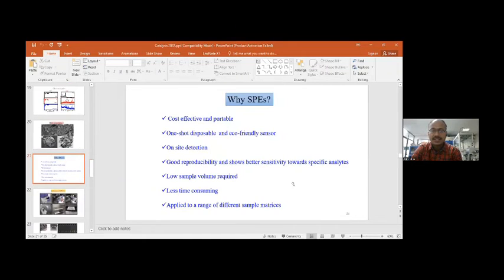Once we get this material, we have taken the screen printed electrode. As I told you, the working electrode can be anything, that is indium tin oxide, glassy carbon, carbon paste, screen printed, but we have taken the screen printed electrode in this particular study because screen printed electrodes are very cost effective, portable, one-shot disposable and eco-friendly sensors. We do not need much time to polish these electrodes, as with other electrodes where we need much time to clean them, and they can be taken to the respective places for on-site detection. They have good reproducibility, require only a low sample volume, are less time consuming, and can be applied to a range of different sample matrices. So this is the speciality of screen printed electrodes.